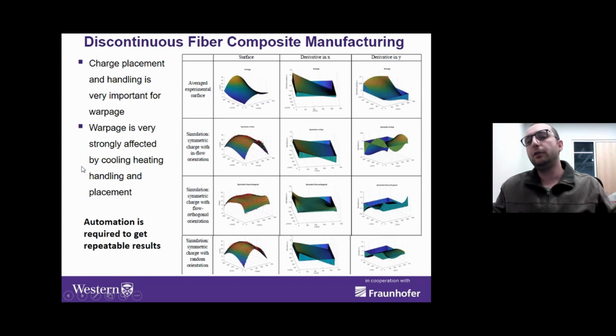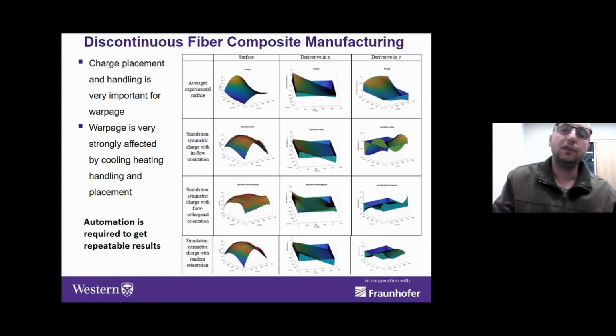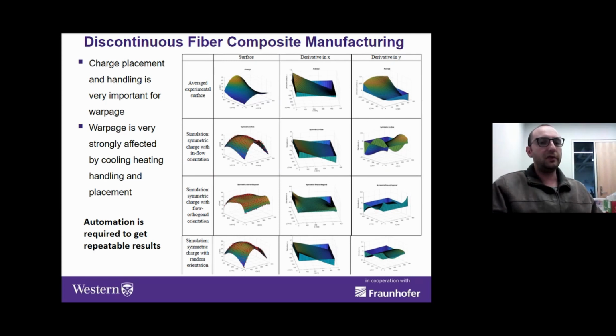So far we talked only about continuous fibers manufacturing, but in discontinuous fiber manufacturing there are also problems, probably even bigger problems than in continuous fiber manufacturing, because now you have another parameter that goes into the equation, and that's how you place your charge into the mold. So here you can see some simulations with it. The top result is the experimental result, and the bottom three results are simulation results. And what we were trying to do is mimic the warpage of the part in simulation to reality. And as you see, it actually was very difficult, and in the end we were not successful.